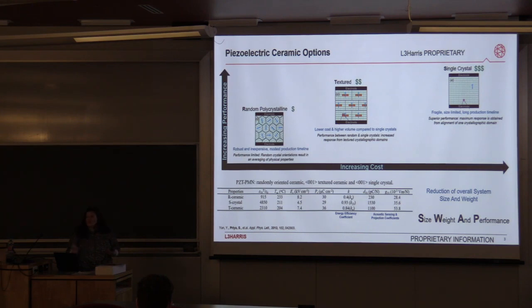And this is actually a 1-domain material. So it is pristine. This is your perfect material. And while it is pristine, it also has some robustness issues. When you're making single crystals, what I'm mostly talking about today is PZT, which is a solid solution of your lead titanate and lead zirconate perovskite structures. And for this, it's actually quite hard to grow a PZT crystal of the formulation that you're targeting and have the entire boule that you're growing be of the same uniform composition. So that's one of the problems we talk about there.